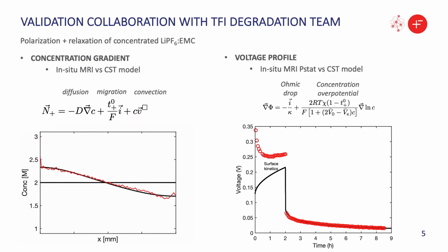They have a technique based on in situ MRI, which can directly visualize the concentration gradients as they develop within a cell. We plugged in our independent measurements for diffusivity, transference number, and partial molar volumes, which parameterize the cation flux behavior across diffusion, migration, and convection.